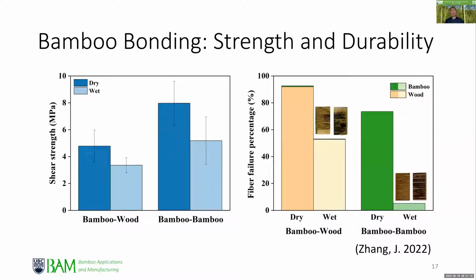And one of the major aspects that also differentiates bamboo and wood composite is the bonding. Bamboo is harder, and so it provides a greater potential for higher strengths. But on the other hand, bamboo is harder because, as we mentioned earlier, there's an inability to penetrate resin. Therefore, there's a problem of creating the durability aspect, which is currently measured by the failure percentage of the fiber, whether it's wood or bamboo. So if you look at it especially when the product is wet, and the percentage of the bamboo or wood failure is very low, that can signal a durability issue.